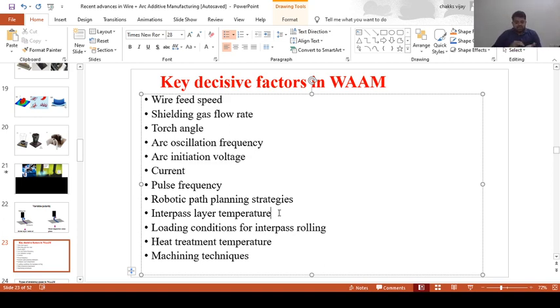For every 200 degrees Celsius, I will deposit one layer. I will wait until the layer gets cooled down to 200, and once this layer has reached 200, then the subsequent layer will be deposited, and we will wait until the next layer cools down. That is otherwise called the interpass layer temperature.